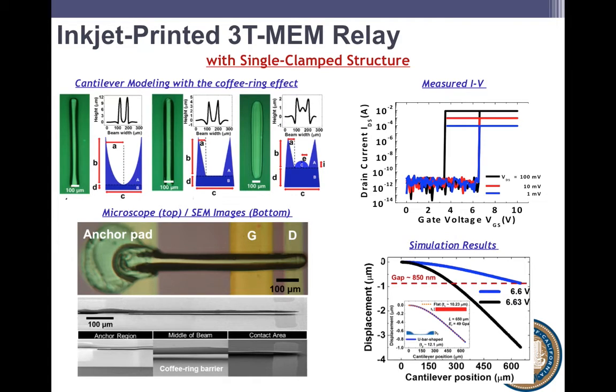So here, again, using the knowledge of fluid mechanics that we've developed, we actually print structures and we pick conditions that print such that we intentionally get ridges. And in a single pass print, we can produce these ridges that then give us a U-shaped beam. This is an example of something that would be really hard to do using conventional techniques. It's really hard to get a structure that looks like this in one deposition process. But we can get it for free by exploiting the characteristics of fluid mechanics, in other words, how droplets dry.